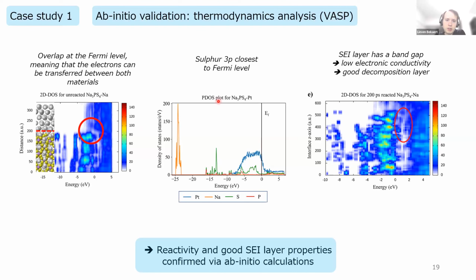When we look at the partial DOS, the projected DOS, you can see that closest to the metal electrons, you have the sulfur atoms. So the sulfur atoms we found were also the first to react. It's the breakdown of these PS bonds. So this once again confirms the results from Matlantis. And you can see also in this figure that we found that there is a band gap for this decomposition layer, for the SEI layer. That also is a good property, which means that electrons cannot easily go into the decomposition layer, which is a good property of a decomposition layer for the solid state electrolyte and sodium metal interface. So the reactivity and the good SEI layer properties were confirmed via ab initio calculations.